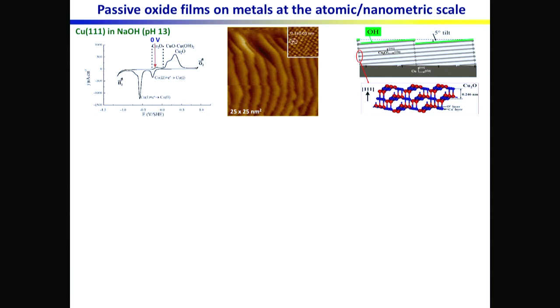So basically you use a tip, you bring it close to the surface so that electrons can tunnel from the surface to the tip or from the tip to the surface by applying a very, very small bias, and the distance is of the order of a few angstroms. Then you scan the tip over the surface and you record a map of the tunneling current, which is a map of the density of states, and that also gives you the position of the atoms at the surface. And this can be done with very, very high resolution, namely with atomic resolution. So in this work, we use a tungsten tip, which allows us to get atomic resolution because it's a fairly rigid metal. So this is one example of a scanned area, 25 by 25 nanometers square.